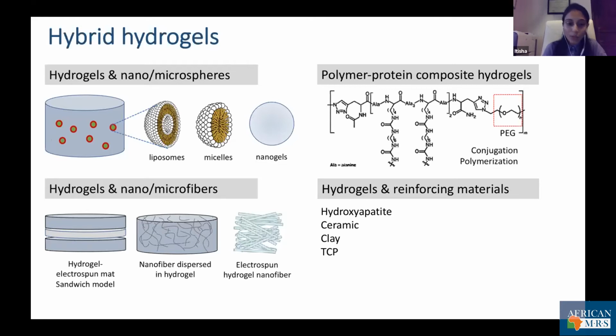Various techniques have also been used to incorporate nanofibers and microfibers. Obviously, we work with nanofibers, we do electrospinning in the lab. So we are looking into hybrid scaffolds where you have the hydrogels incorporated with these nanofibers, either to improve the mechanical properties or to induce synergistic biological properties of an electrospun mat or a hydrogel. So you have a sandwich model, either dispersing the hydrogel, or in terms of electrospun mats, with each fiber actually being a hydrogel, which can retain water.